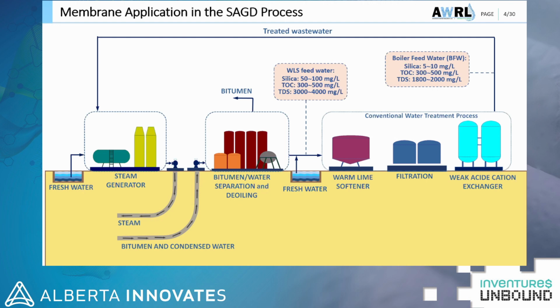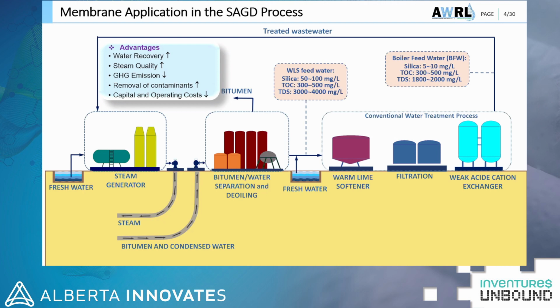There are some challenges in the current process. The high concentration of dissolved solids and organic matter in the boiler feed water, or BFW, causes the fouling or scaling of the boiler tubes, so they must be cleaned or replaced more frequently, which increases the operating cost of the process. Also, if we can increase the quality of the boiler feed water, OTSGs can be replaced with drum boilers, and therefore we can increase the steam quality and water recovery. We believe that the conventional methods can be replaced with membrane processes to increase the water recovery, water quality, and steam quality, and reduce the GHG emission and operating cost of the SAGD.